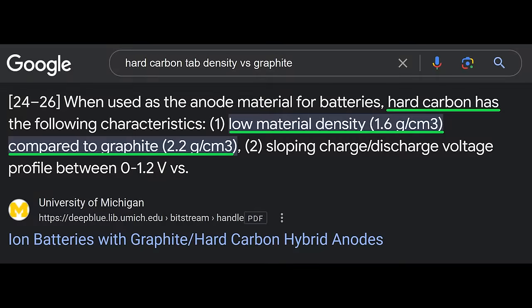And the problem with hard carbon: if you put 1 gram of graphite and 1 gram of hard carbon, the volume difference would be huge, because hard carbon, disordered carbon, is a really fluffy material. That severely limits the volumetric energy density of sodium ion batteries if people use hard carbon. Up to today, there's still debate about exactly what the mechanism is for sodium versus hard carbon, how sodium enters the hard carbon. I think a lot of studies have shown that sodium does intercalate into the hard carbon, and it can be reversible. So the only problem is that hard carbon has very poor volumetric energy density. It occupies a lot of volume and hosts not a lot of sodium. So, all right.